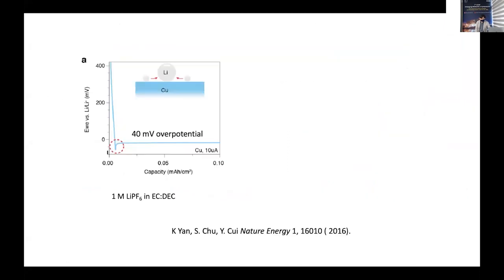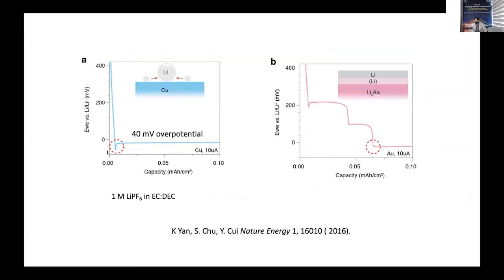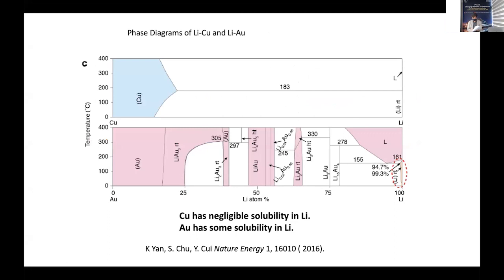So let me share with you some examples of design. First of all, how does the lithium plating happen? We use all types of substrate for lithium plating when we build the batteries. For example, copper is commonly used. We find that on the copper surface, lithium plating has an overpotential. You see this voltage dip, and then lithium nucleation and plating happen. And on some other substrate, on gold for example, the first plateau at 200 millivolts is the lithium-gold alloying, and then after the second plateau the lithium plating happens close to zero potential. In this case, you don't see the voltage dip anymore. So you really don't have the lithium nucleation barrier right there. So this is very different. Copper and gold, the differences are just gigantic. It's due to the phase diagram.